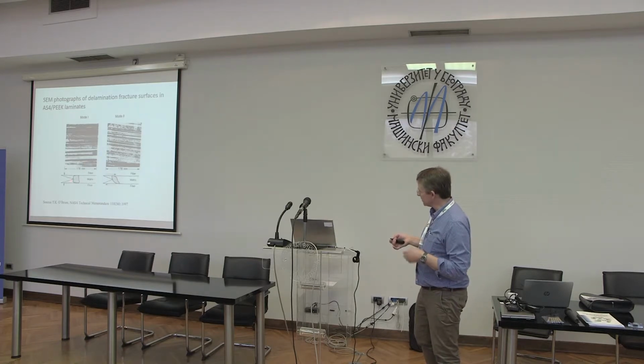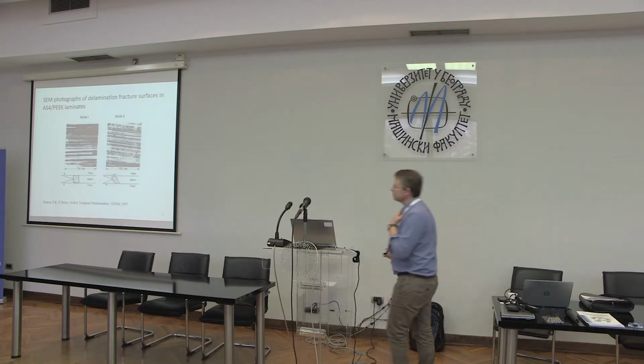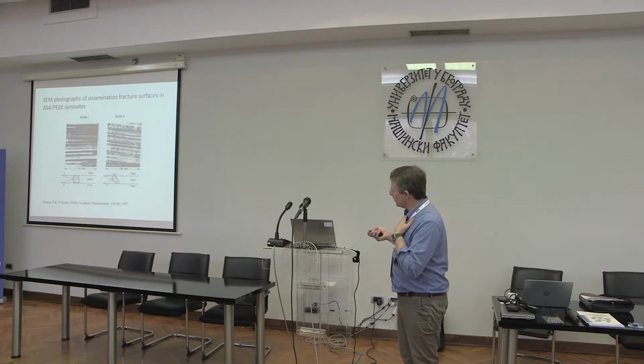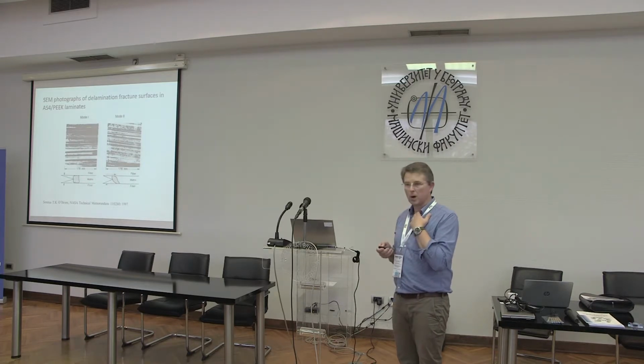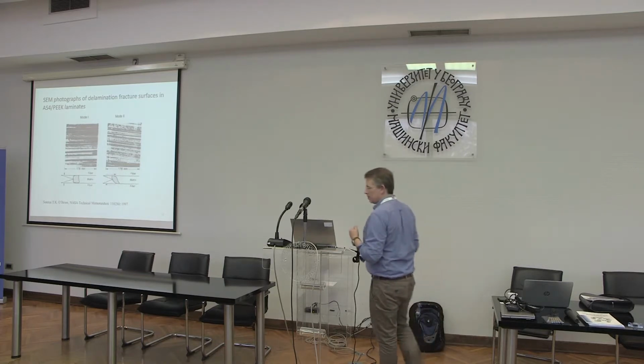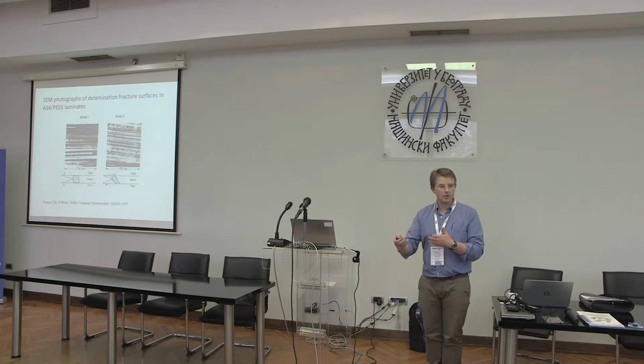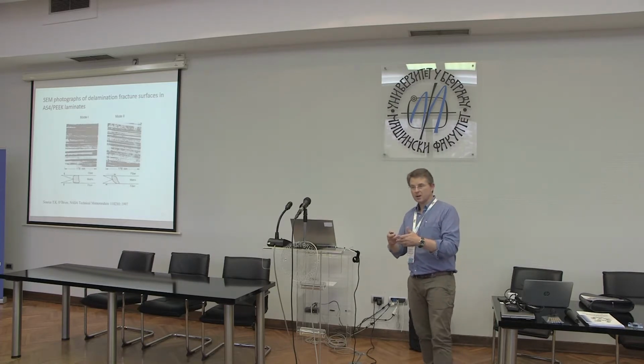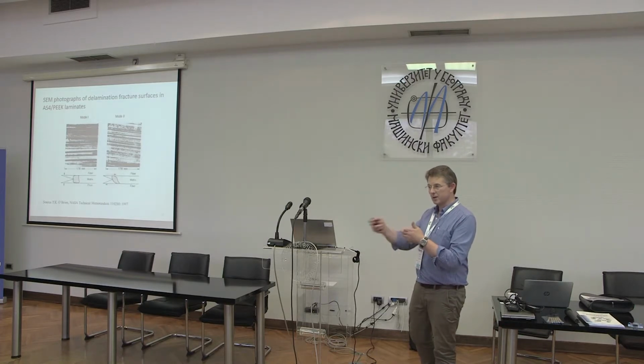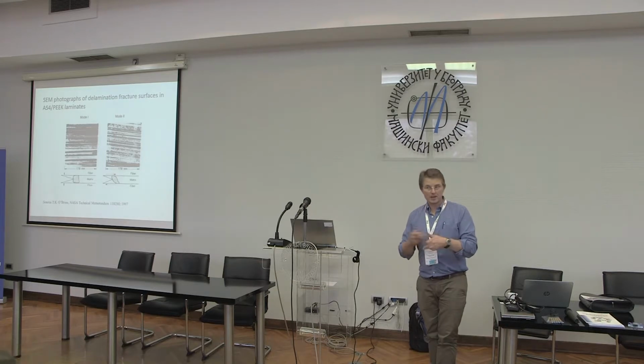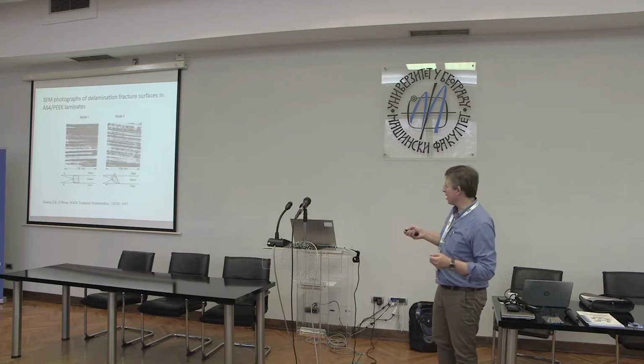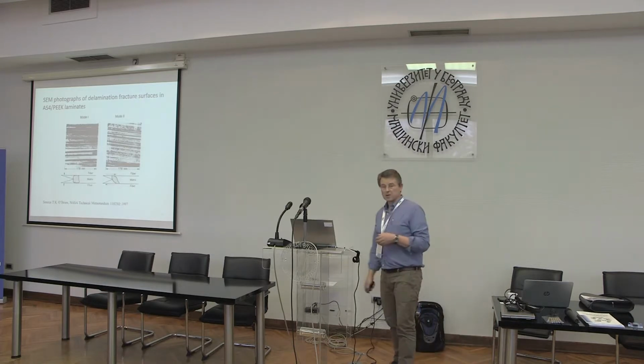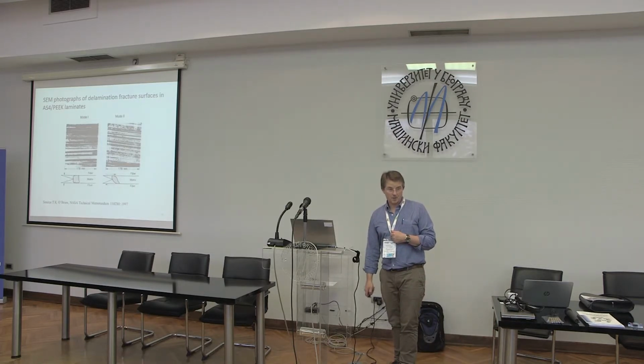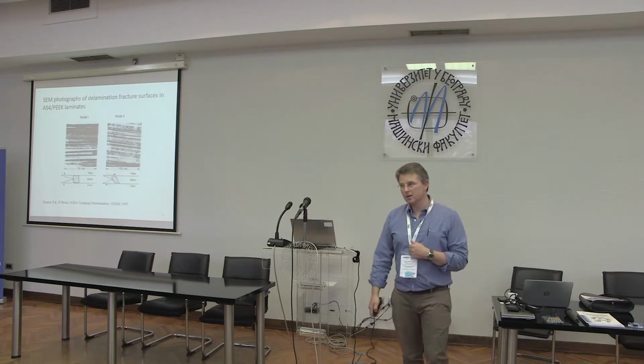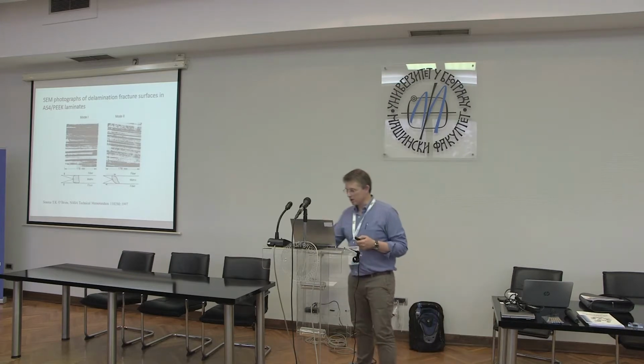And what this was put down to, so these were Kevin O'Brien's slides, but he put forward the notion that if you have a relatively large plastic zone here in mode 1, that stops the tensile microcrack mechanism actually kicking off. So because of the extra ductility, you don't get the elevation of the stresses required to generate the tensile microcracks ahead of the main crack tip. So the micromechanics of the process is different. So what actually happens in the mode 2 situation is that simply the damaged zone rotates, but is about the same volume or area in 2 dimensions if we're looking at it here. So you imagine a more or less similar total energy dissipation.